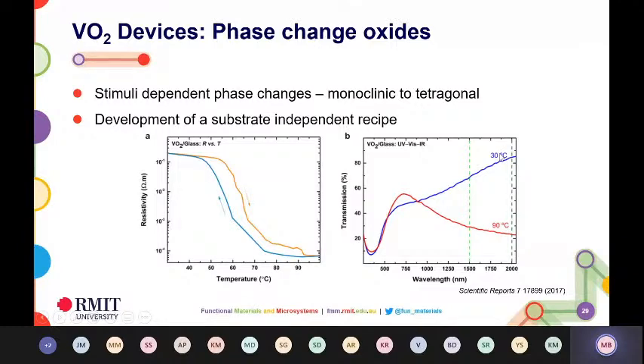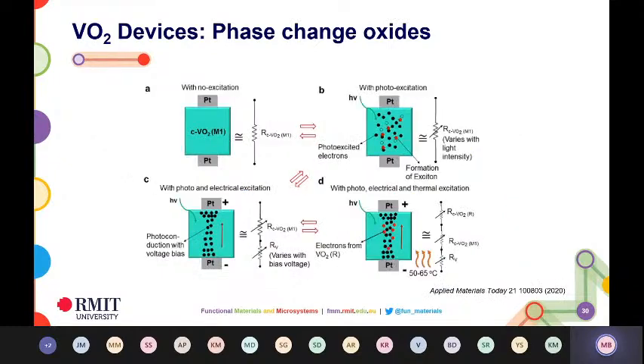So we did some work in this particular space where we managed to develop a substrate-independent recipe. Until then, a lot of the vanadium dioxide was deposited on sapphire or lithium niobate or really expensive substrates. We managed to get this working on glass, on silicon, on most standard substrates. So that allows for easy integration into electronic or optical devices. So it's a fascinating multi-stimuli material. You can excite this using light, so using photo excitation, you can excite electrical impulses, or you can excite it thermally by heating it up.